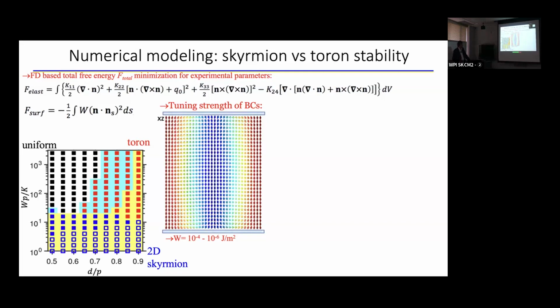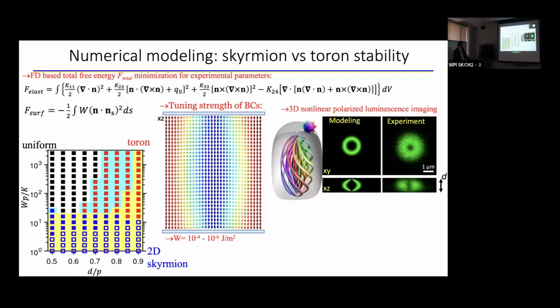And of course, as I already mentioned, the one of interest for us for this application are the torons. And so we find that they are stable in this range. Then we form them and we can image them. So we can reconstruct them from numerical modeling that utilizes minimization of free energy and gives us this type of field configurations that can be visualized with the help of pre-images in the form like you see in here, where for every point on the surface of the order parameter space, we have a region that connects two point defects, Bloch points, and has this chiral configuration.